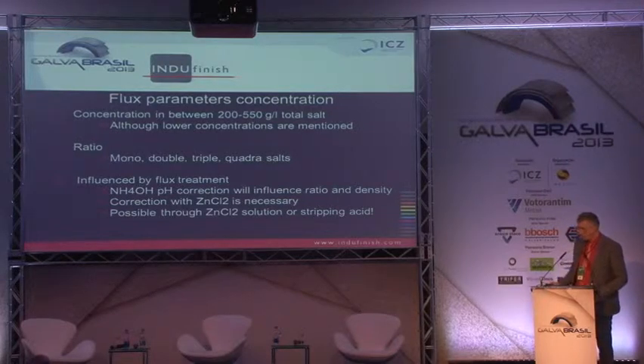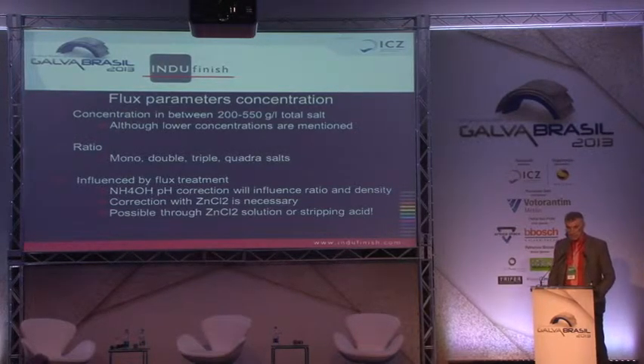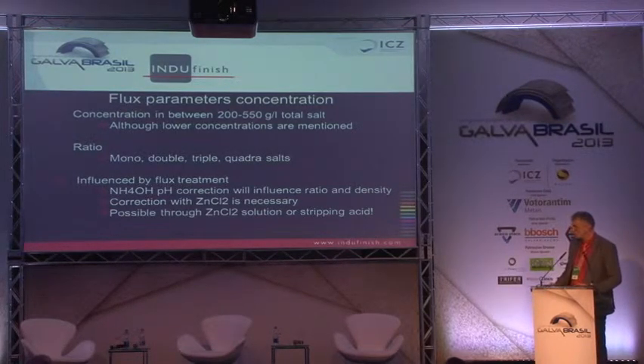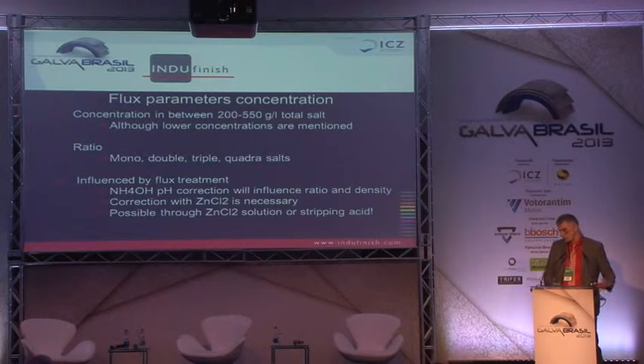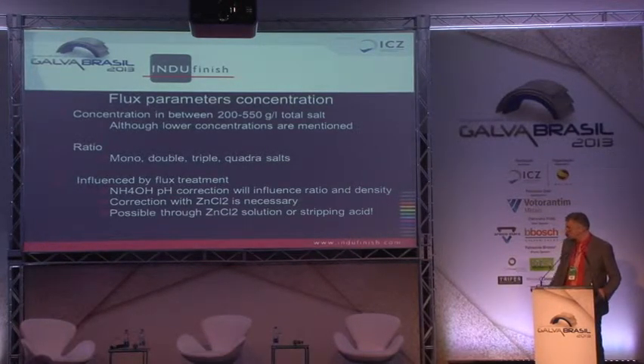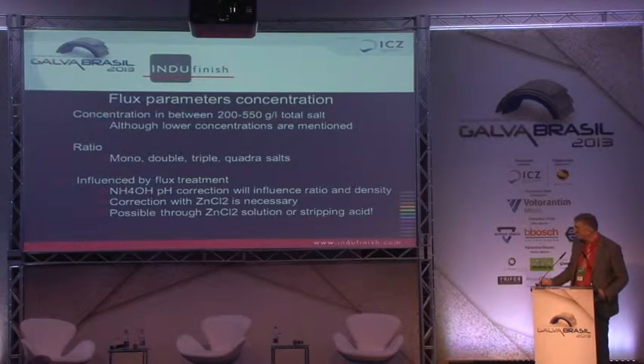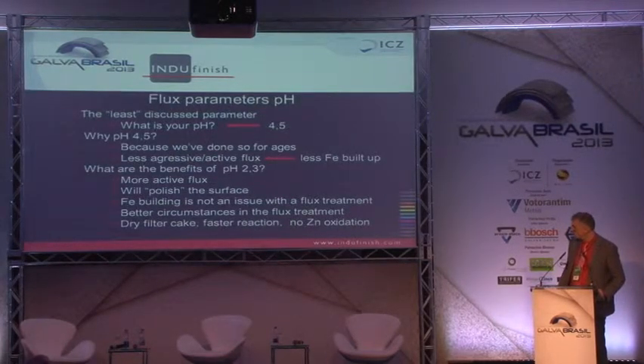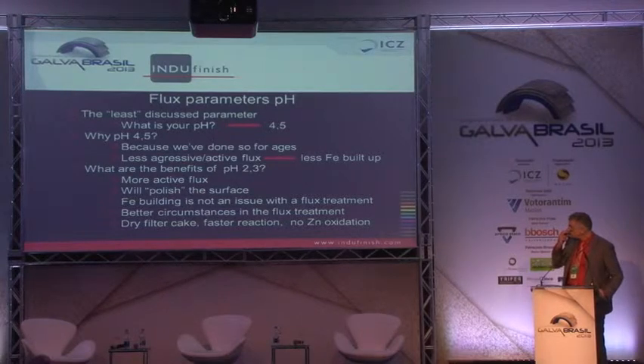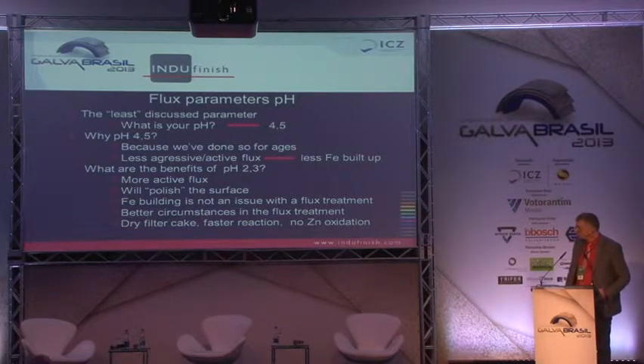And if you don't have a strip tank, if you don't have stripping acid, you can dose fresh zinc chloride. Otherwise, we will take the zinc chloride out of your stripping acid and dose it, and therefore your concentration will be in shape. Then pH. That's quite a different story.